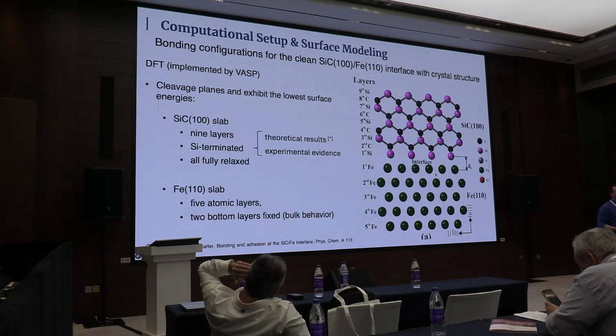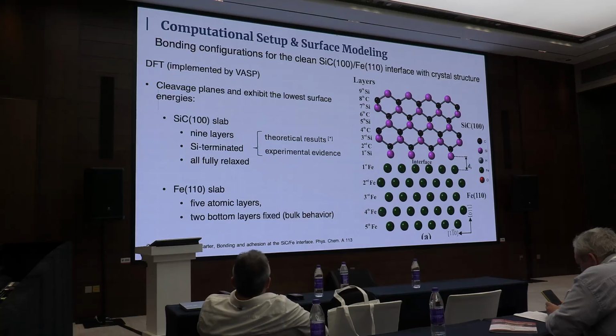So because of that, we will only relax 3 layers and fix 2 layers in the bottom. These 2 layers were fixed with the same parameters that the bulk has. So we will reproduce the inside of the material, as the material goes more deep in there. So yeah, this is the configuration setup we chose.